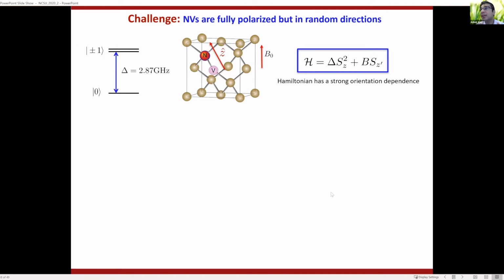And so the key challenge in this entire enterprise is the fact that while these NV centers polarize, I didn't tell you in which direction they polarize. If you shine light on these particles, or on diamond, the NV centers are quantized in a very specific direction in the lattice. And this is one of the problems of a solid state medium. Solid state media give a lot of advantages in transportability, and it's really a physical thing, so you can move it, unlike a gas or a liquid, which is more difficult to physically localize. Here, a solid state medium is very amenable to all kinds of tricks that you can do on the outside. But the problem is that there is a definition of a lattice, and the electron is quantized in a specific lattice direction.